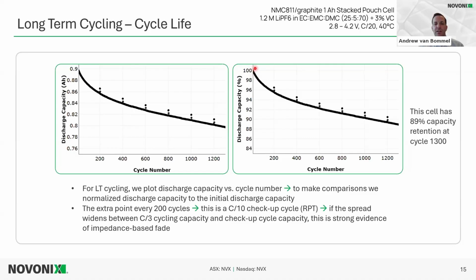We don't see something that's perfectly flat. There are some losses during cycling, especially when we look, this is C/3 rate. So we're not cheating the clock or beating the clock by doing faster cycling in this case. And so we have C/3, and then we are also at a little bit of an elevated temperature to allow for more degradation mechanisms to occur. So it's just a little bit higher here.